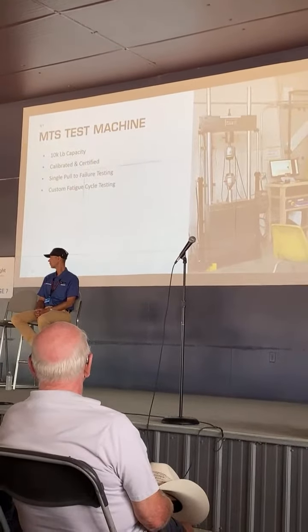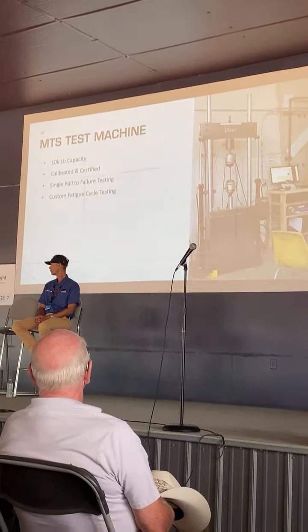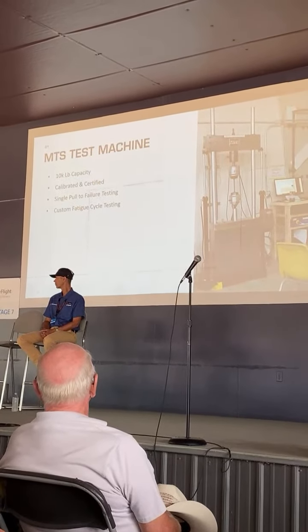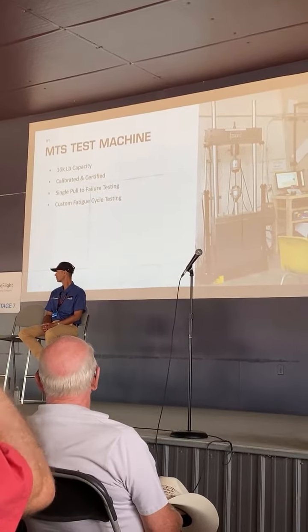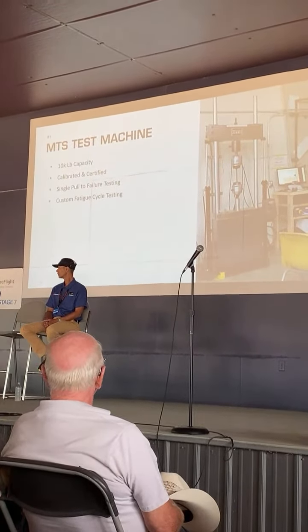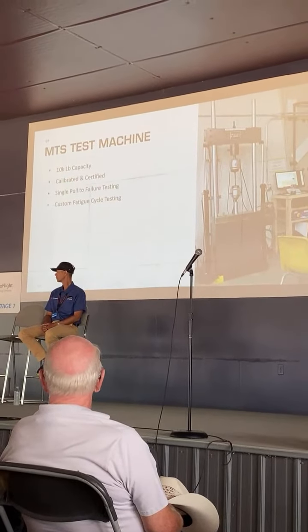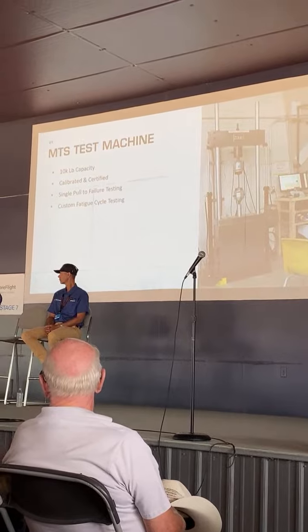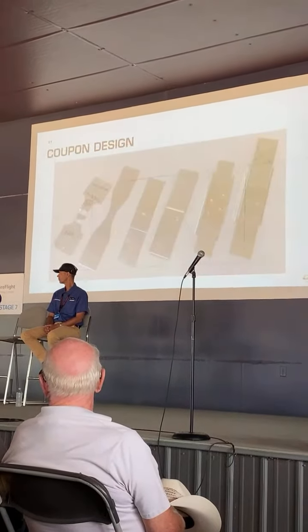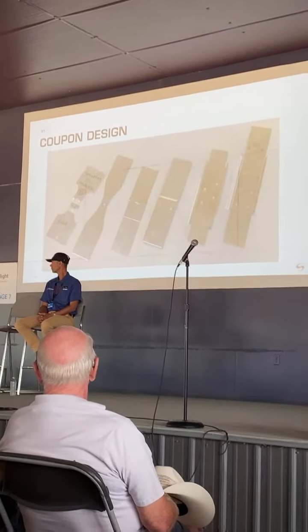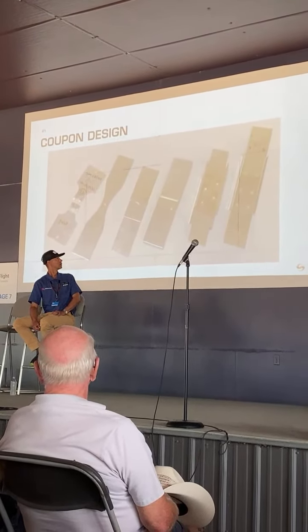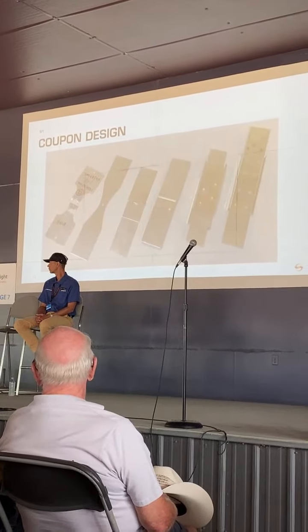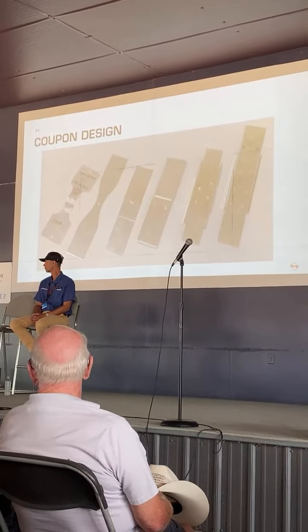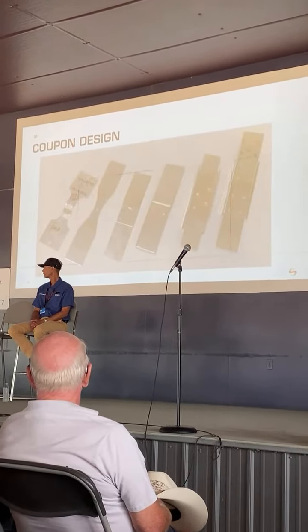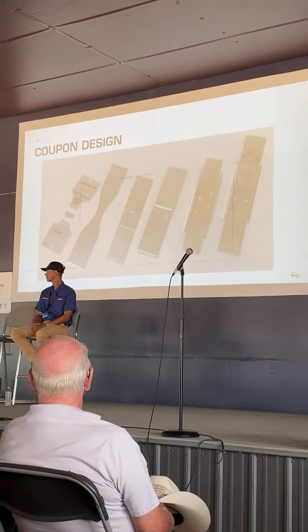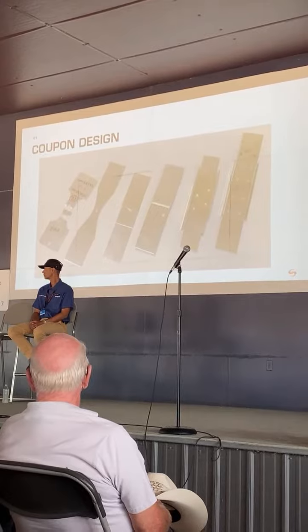Here's the machine that we use. This is a calibrated and certified machine. It's the MTS test machine. We can do pull test, tension to failure, as well as tension and compression cyclic testing. We can even set up a specific cycle if we wish to do so, program it into the machine. Here's an example of the different types of coupons we've done over the years. And just to be clear, the coupon on the left was from our testing in the late 90s. This starts out in '99 when we were trying to go to final sized holes. So we've been testing this way and at local universities for some time.